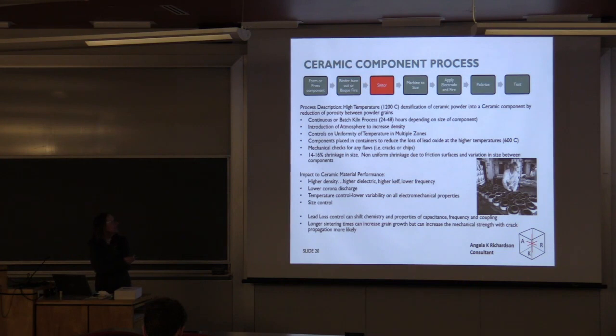The next step is the densification, the sintering process. With a PZT-based material, you're going up to about 1200 C, and you're processing it for about 24 to 48 hours. In manufacturing, it's so critical. As students, you might be doing some firing in small kilns, but when you think about a kiln that is essentially 6 feet wide, 10 feet deep, when it's that large, if you don't have uniform temperature, what you're going to get is non-uniform product.